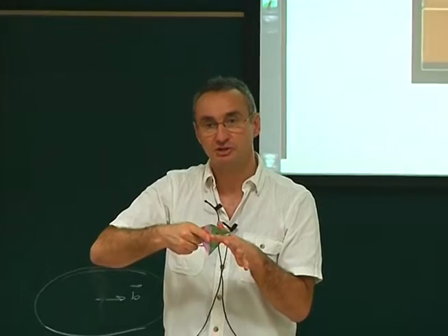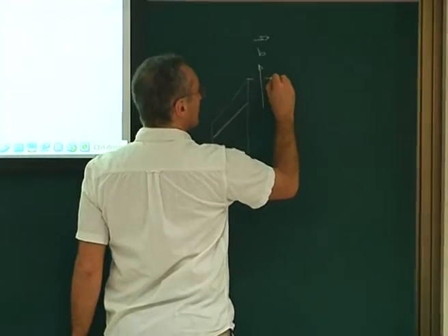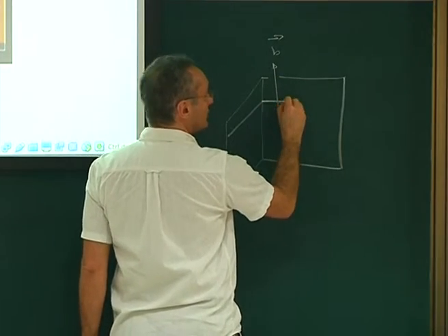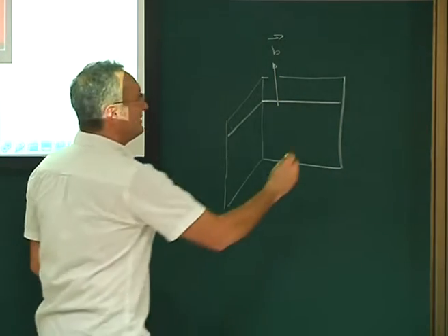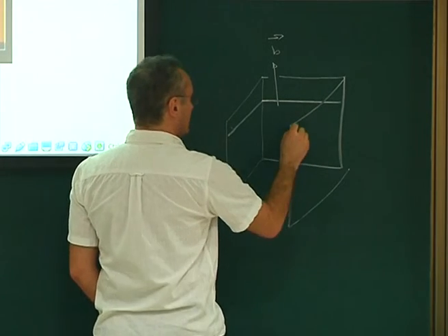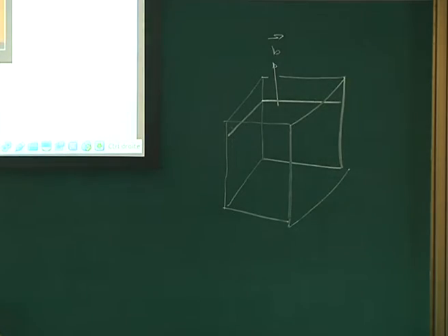Then you know that in your Thompson tetrahedron here, this is my Burgers vector, this is my edge dislocation. I can have another edge dislocation which shares the same Burgers vector, which has an angle which is not 90 degrees, an acute angle. So here I can define another plane, like that, which also shares the same Burgers vector. So here I can put another edge dislocation. And then I can close this loop by another plane, like this, and a fourth plane here.